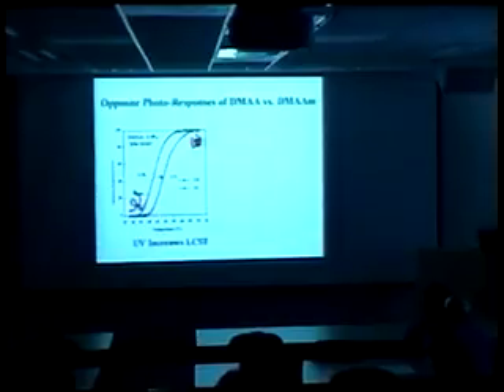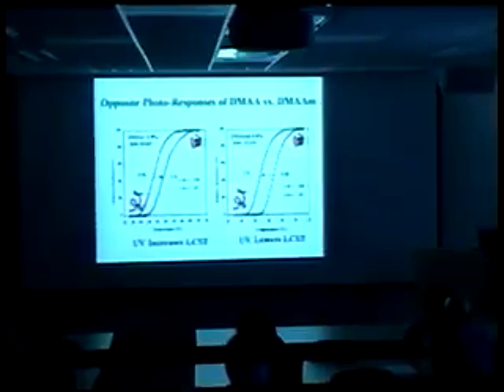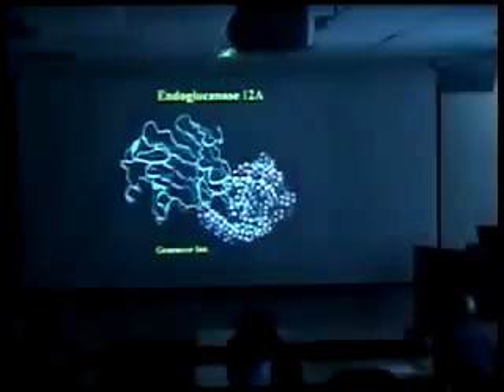And so at that isothermal temperature, by shifting the polymer between these two photoradiation states, the polymer exists either more collapsed or expanded. And the interesting thing that we still don't understand very well is that the amide-linked polymer goes in just the opposite direction. So UV lowers the LCST. So you can just go in the opposite direction, which may be important for some applications, but not so important theoretically.